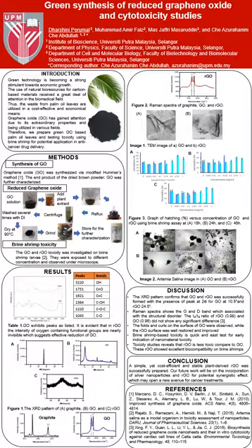The results of the main characterization performed are as listed. FTIR was conducted to identify the biomolecules that are responsible for capping, reduction, and stabilizing. Based on the peaks listed in Table 1, graphene oxide exhibits a peak at wave number 3220, which is assigned to the hydroxyl group.